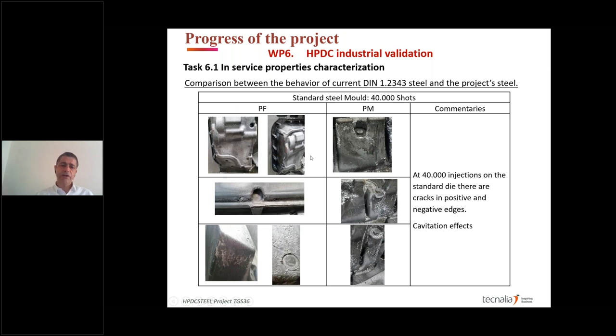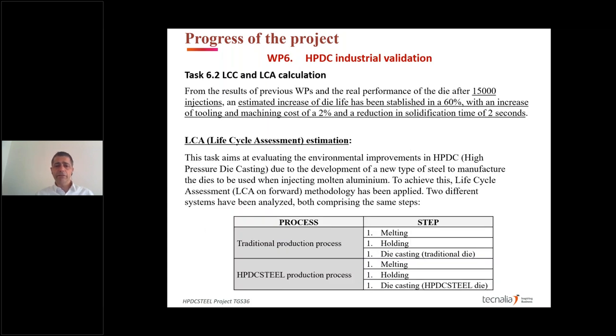But we are making comparisons between the real state of the new developed die and the standard life with premium steels. And we have made an LCC and LCA calculation with the new data. The new data, after 15,000 injections, we have an estimated die life increase of about 60%. We must check, but by the moment we are very comfortable with this data.